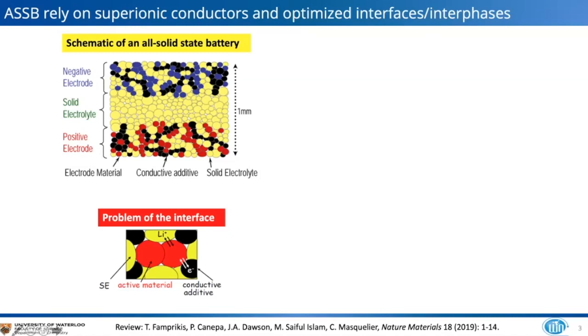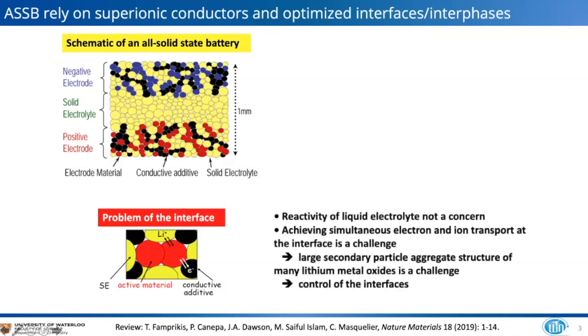So the problem is, of course, developing good solid electrolytes, but it's also a problem of the interface, the triple phase boundary, where at the active material, for example, the positive electrode, lithium ions and electrons have to be simultaneously transported to that active material. And that requires very intimate interfaces. So while the reactivity of the electrolyte is not a concern, achieving this simultaneous transport is indeed a challenge. And if one has large secondary particle aggregates, that's also a challenge to obtain an adequate interface.